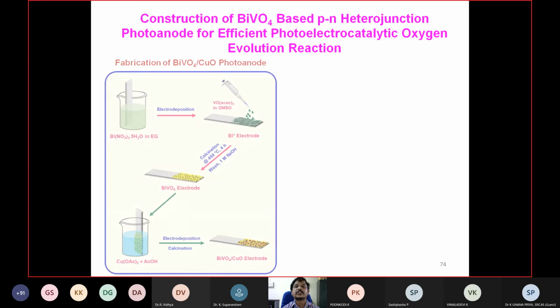Okay, so this fabrication method is slightly different. It's not like a conventional hydrothermal or solvothermal method. Here we have developed the material over the electrode itself. For that, we have taken bismuth nitrate and ethylene glycol. We dip the electrode into the solution, then we applied a certain potential.